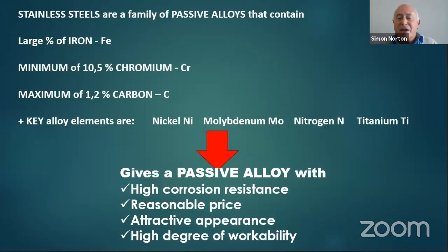Now, stainless steels are a family of passive alloys, largely of iron, with a minimum of 10.5 to 11% chromium that forms the passive chromium layer, the chrome oxide layer on top of stainless steel. This is the heart of the secret of stainless steel. The key other elements that are added in are obviously nickel, molybdenum, tungsten, nitrogen, and there are others such as copper, niobium, and those make for special stainless steel alloys.